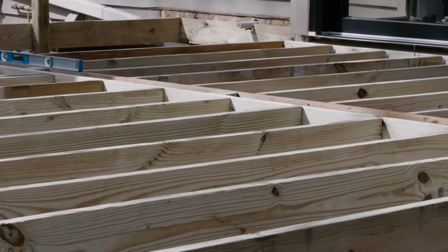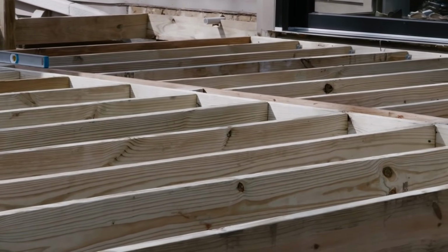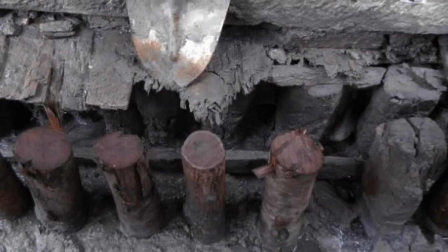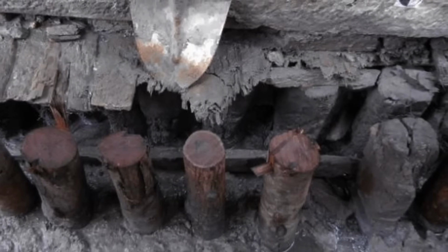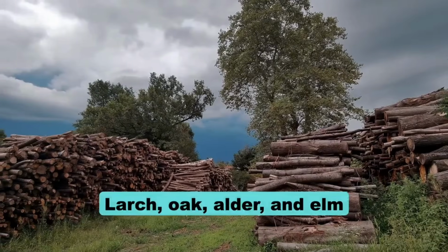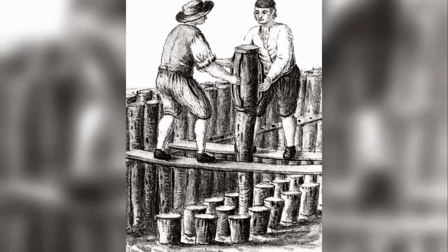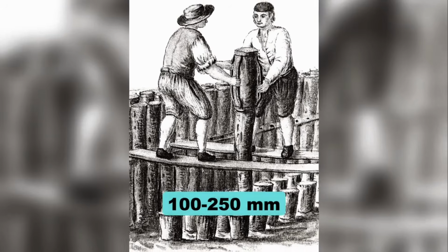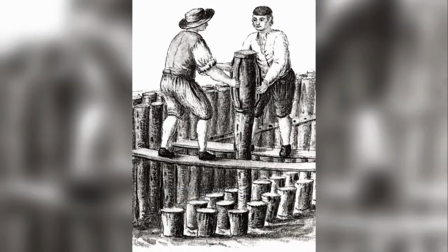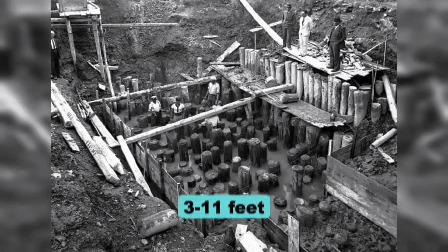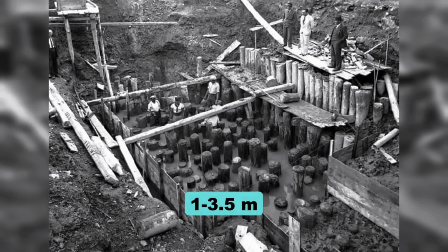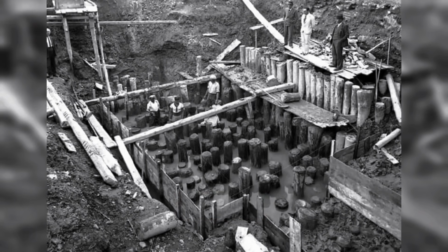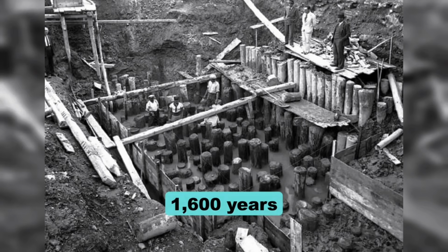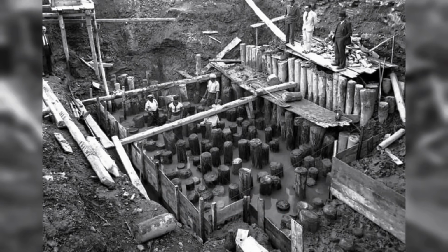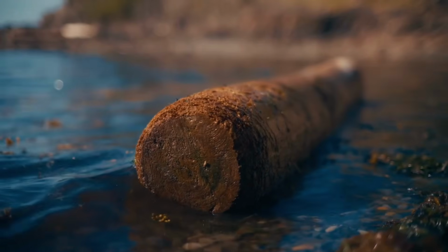diagonally across each other and pressed into the saturated ground. Venice drove somewhere between 8 and 16 million wooden piles, mostly larch, oak, alder and elm, each only 4 to 10 inches, 100 to 250 millimetres, across and 3 to 11 feet, 1 to 3.5 metres, long, into its lagoon bed across 1,600 years. These foundations should not last.